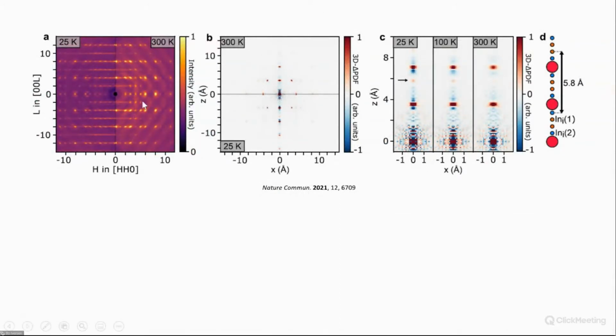So how about this? It should give diffuse scattering also, and indeed it does. It's not very strong, and there are some features one can interpret here, but I'll just draw the attention to this feature here, because this is one of the features that disappear as we heat up and get this sausage through the structure. So at low temperature, there is this 5.8 angstrom correlation, and this is because basically if I have an indium atom at this site, then I also have an indium atom at this site. But as we heat up, the correlation disappears, and I just have a totally disordered sausage through the structure.